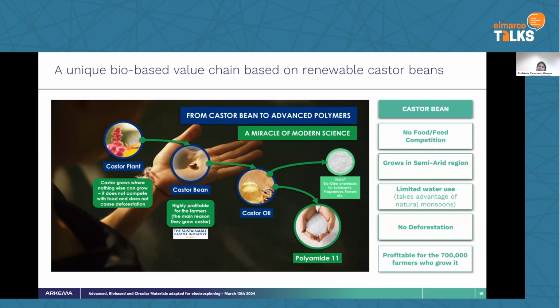So Arkema buys the castor oil, and here we will split it, so it's a molecule with 18 carbons, and we will have the chemistry of our C7, also valorized under our product range Oleris, so some lubricants, flavors, fragrances. So it's really important to valorize all the value chain. And the chemistry for our C11 will give birth, I would say, to our monomer, which is an amino carboxylic acid. So we need only one monomer. And then we polymerize and we obtain the polyamide 11. So Arkema is fully integrated from the monomer to the polymer.